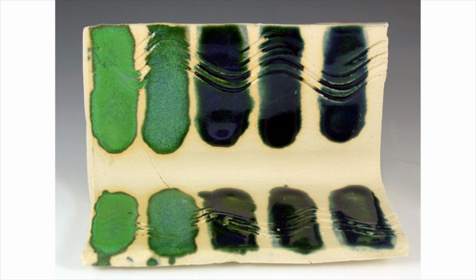So to sum up this series of glaze tests, I showed how to adjust a glaze by taking out all of the flux ingredients in the recipe and then adding them in, or the clay component and adding it back in, or the silica component and adding it back in 5 to 10% increments.